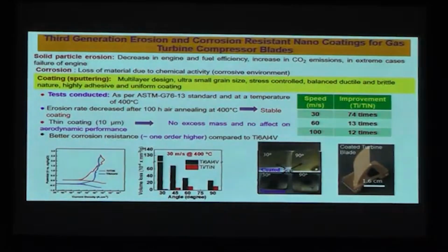And we have also developed a third generation of erosion and corrosion resistant nano coatings. This is by the sputter coating process, that is the DC pulse laser sputter coating process. Here you can see these coatings are developed mainly for compressor blades, wherein solid particle erosion is a major degrading issue for the components. Solid particle erosion is the major issue, which decreases the engine efficiency and increases CO2 emissions and other types of engine failures.